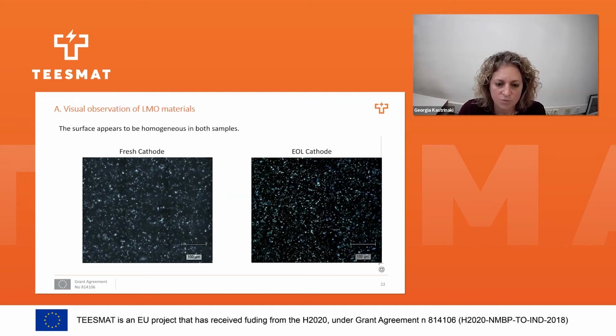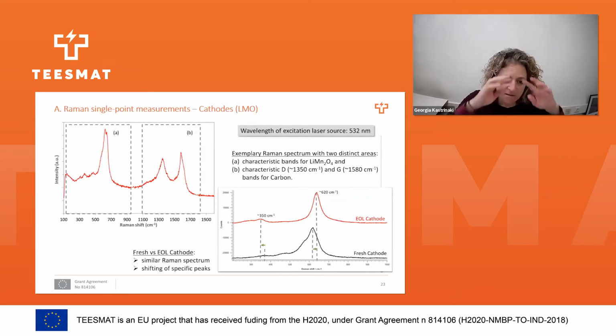But if we go to the chemical composition, first of all, we need to analyze our spectrum so we can understand exactly what are the types of bonds that we are trying to study and we're expecting. So this is the spectra that we get from the LMO. We can divide it into two major categories. At the high wave numbers, we have the active carbon part, and at the beginning of the spectrum, we have the LMO part. And what we saw when we compared the spectra of the fresh and the aged cathodes was that we had a shifting of this main peak that is attributed to LMO. We'll show you in a while exactly what we are talking about.